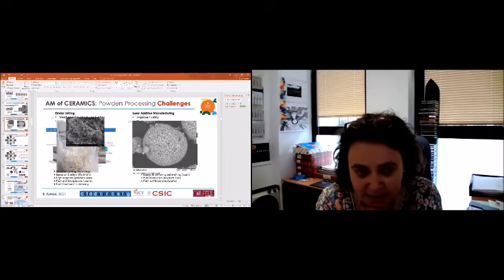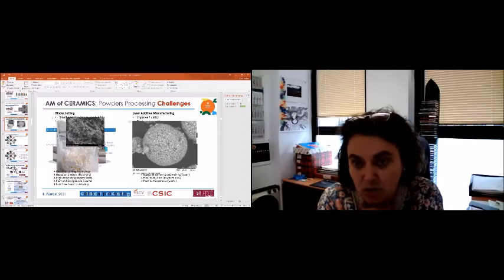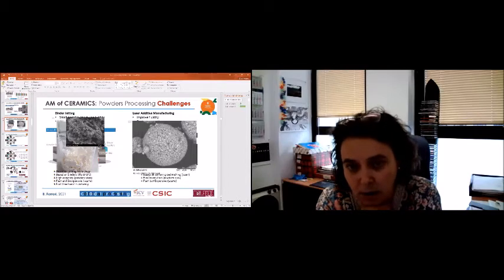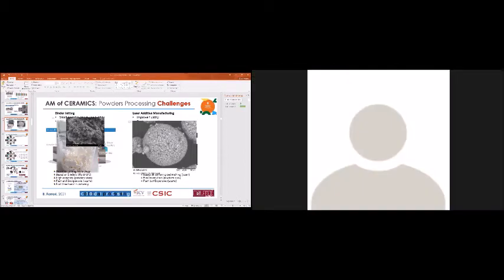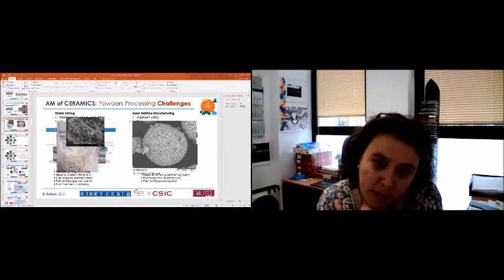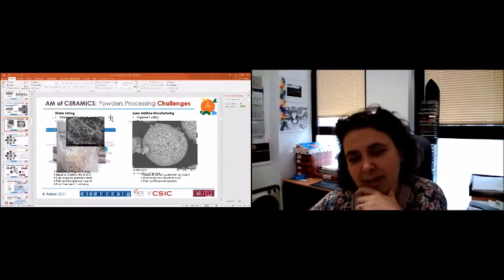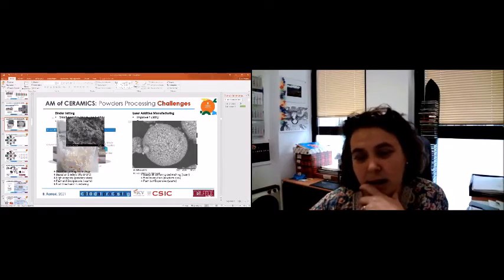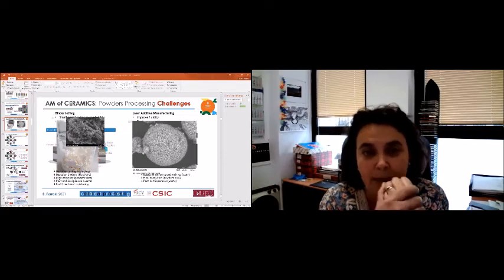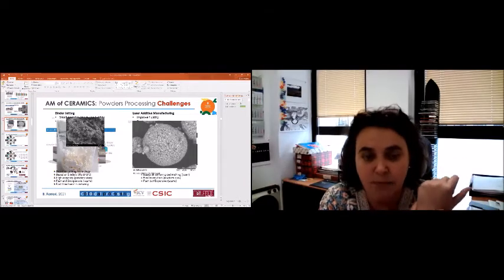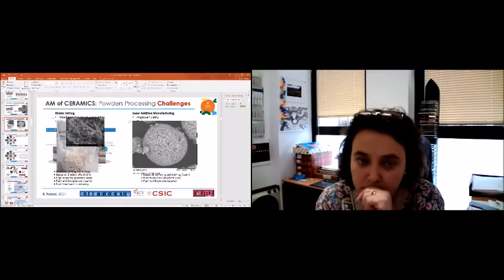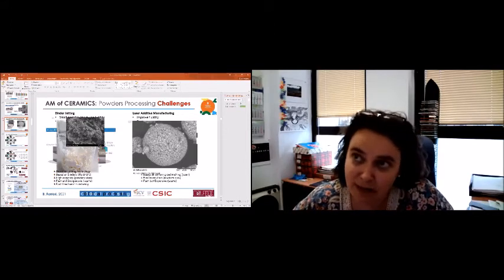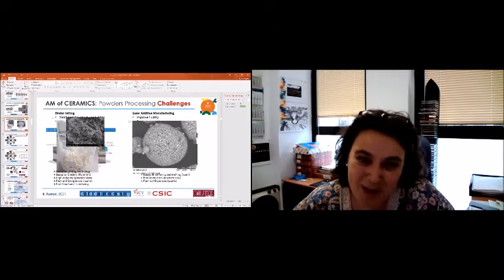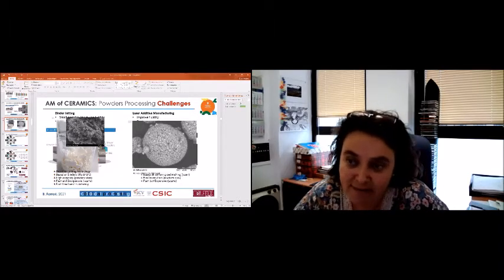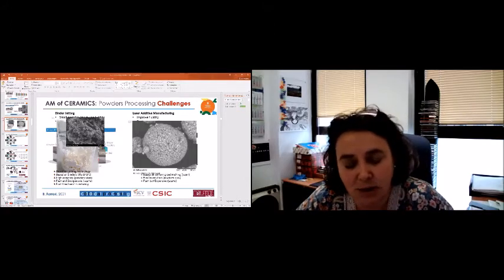That is really complicated because you have two kinds of binders here. You must play with binders to make the granule, right? And most of the people are working right now with mixing in dry, like pressing. People use binders that we use regularly for pressing powder, right? You have this kind of material, more or less. And to move to a material that gives you better fluidity, you must go to spray drying or freezing. And I can tell you that for pressing it is working very well, because you are increasing the size of the powder, and fluency here is really important.